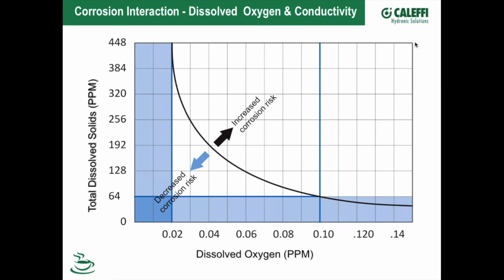Is that right, Kevin? Yeah, it stabilized. Tend to stabilize. I have an example of a system that was installed 16 months ago, and that happens to be my personal hydronic system, but I have about 2,000 feet of oxygen barrier PEX, and just a standard couple of cast iron pumps. I used city water that we measured at 358 parts per million, which is 21 grains, which is going to be higher than a typical boiler spec. And the pH was 8, so that was my city water supply. And when we filled the system with the Caleffi demineralizer, coming out of the demineralizer, the ppm was really low. It was just in the single digits, and the pH was a little bit low at 6.